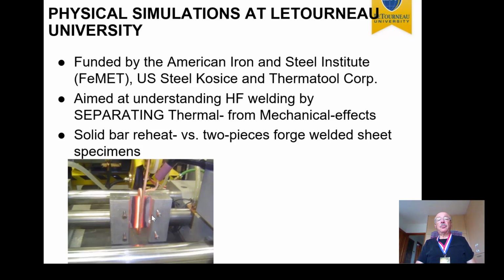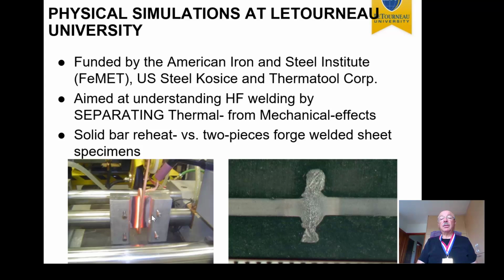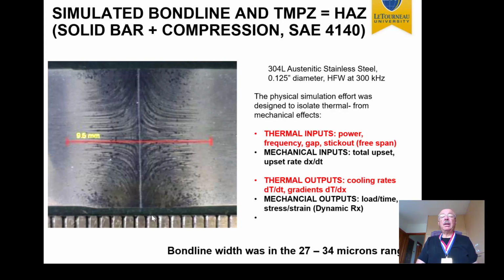And again, solid bars, you can see here; we also looked at welded sheet. We modified this for dual phase 600. You can see two sheets brought together and welded along that line. And here's an example. Maybe excessive flash, which we haven't reviewed, but it was a good quality weld nevertheless. So what we found is that mostly what really varied was the width of the thermomechanically processed zone. This is actually a simulated weld. This is not an actual weld, although it looks very similar to an actual weld.